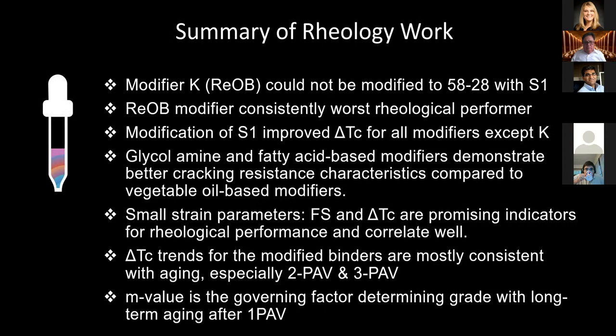Brief summary: modifier K, REOB, could not be modified to a 58-28 with binder S1. More work will probably be done with that one, but it was used to ensure that it was consistently found to perform poorly, because we know that in the field in Illinois REOB is not a successful modifier for us. That was in fact the case through all the tests that were performed. The modification of S1 improved delta Tc for all of the modifiers except K. Glycolamine and fatty acid-based modifiers demonstrate better cracking resistance characteristics compared to vegetable oil-based modifiers.